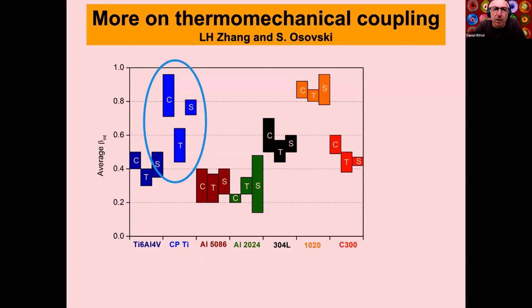So we wondered about that, and the answer was pretty straightforward. When we did metallographic sections, or metallurgical characterization of the specimens, we saw a lot of twinning in compression and shear. The twinning was absent in tension. So we came to the conclusion that twinning is a strong heat generator, and that was already noticed in another context by a team in Chicago, by Padilla and John Lembros. They reported that. So one cannot dissociate the thermomechanics, or the thermomechanical coupling, from the deformation micromechanisms, and we're back to metallurgy at the end of the day.